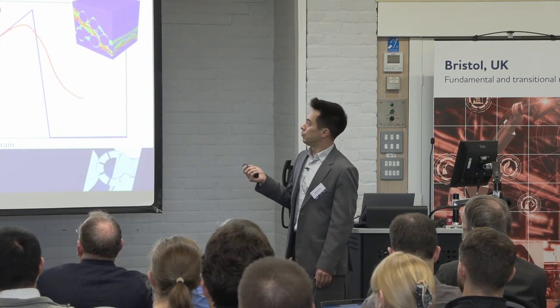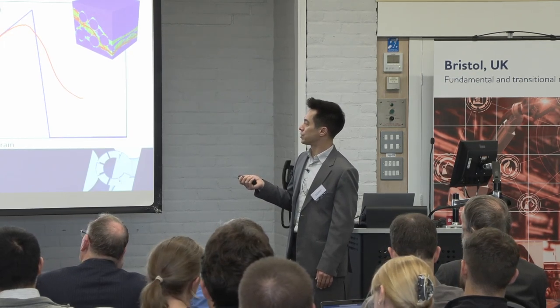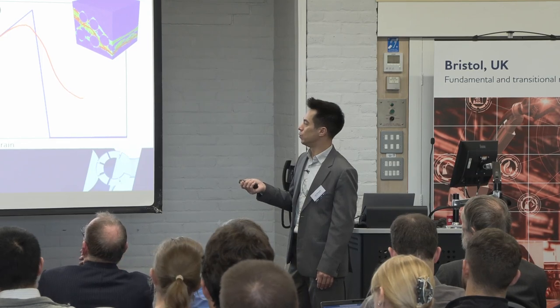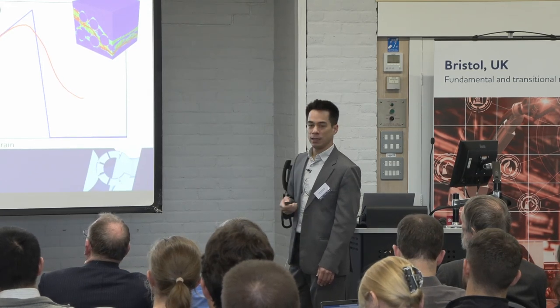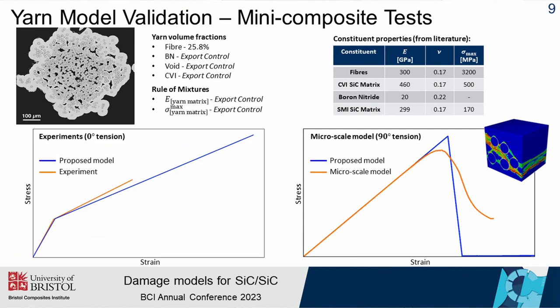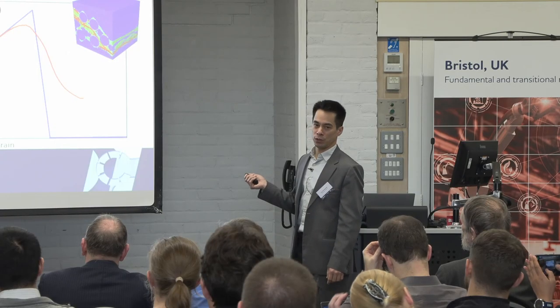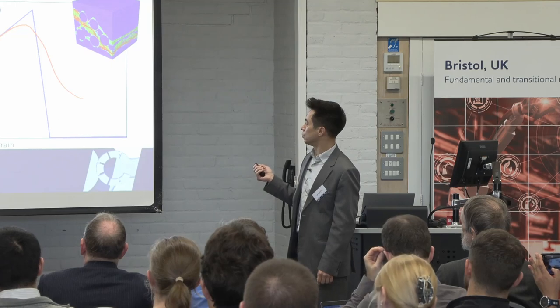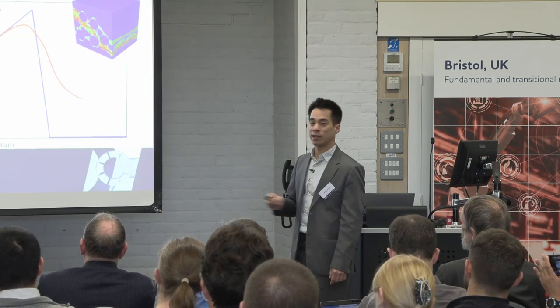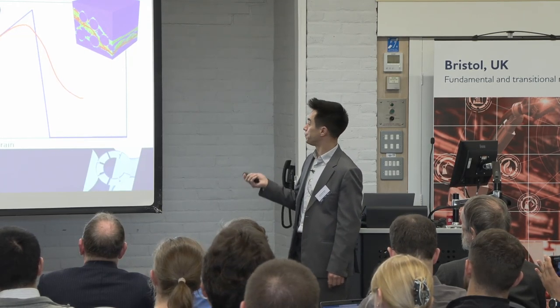The model has been verified against experimental data, so we can see model and experiments in one case here for what we call the mini composites, so approximating a single yarn, and then also against microscale models of these yarns conducted through the PhD of Ricardo Mano within the UTC as well.